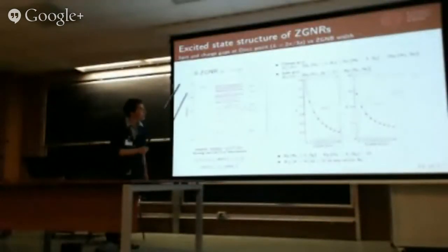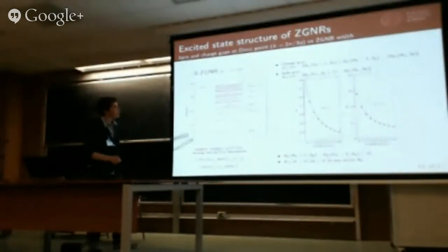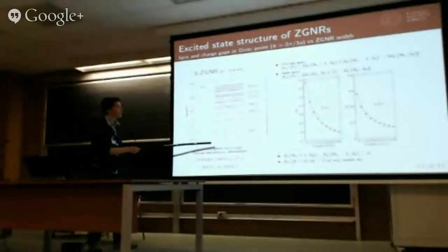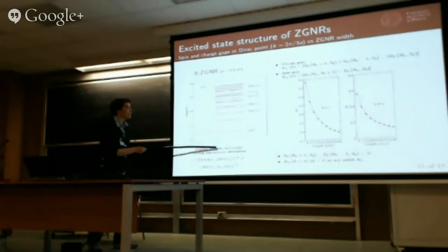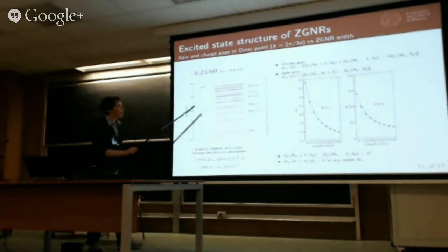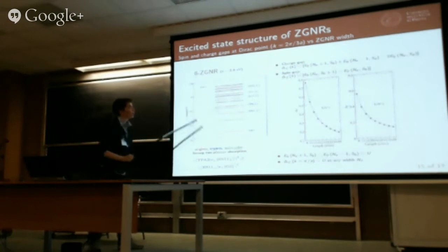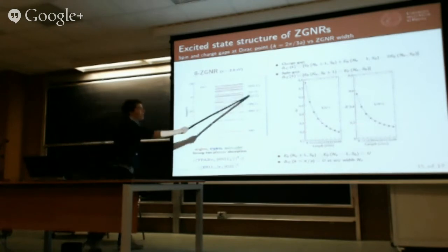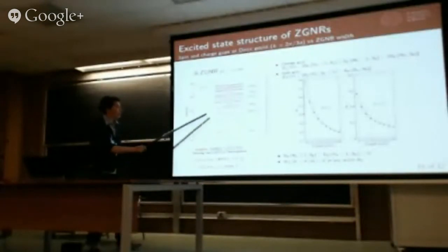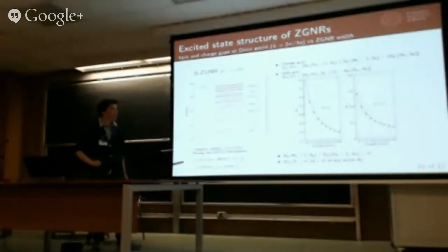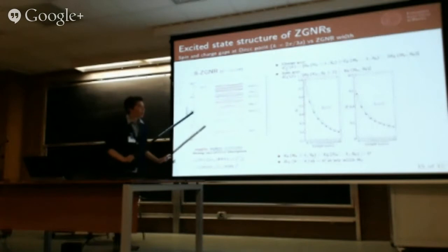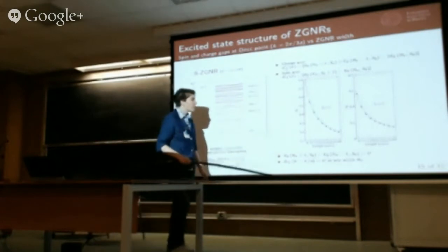This is the excited state spectrum of zigzag graphene nanoribbons, which shows an alternating sequence of triplet and singlet dark excitons at low energies. And I found also a very intense two-photon active state, this one, which is also more intense than the lowest bright singlet excitons. Such an effect was not found for armchair nanoribbons.